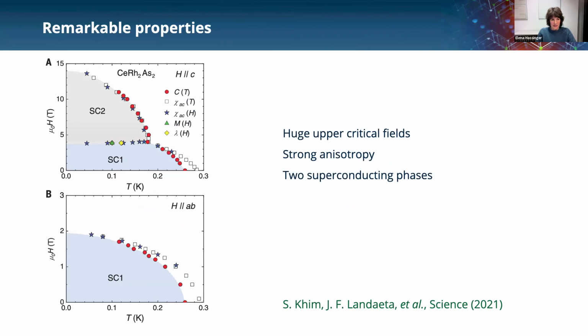So here's the experimental phase diagram for both magnetic field directions. This is the one you've already seen. And there are several remarkable things. Tc is low, as you've heard. It's just 0.3 Kelvin. But the critical field is extremely large, strongly exceeding the Pauli limit with 14 Tesla. And then, of course, there's this strange kink and the phase transition between the two superconducting states that we detect in susceptibility, in magnetization, and also in magnetostriction.